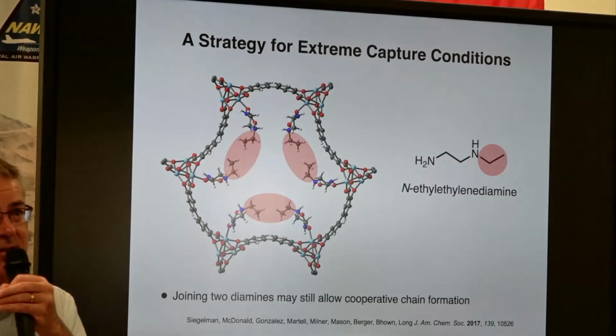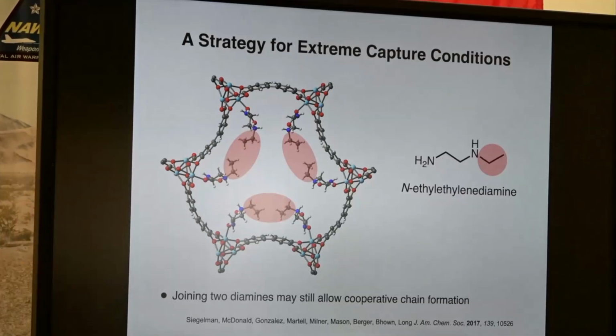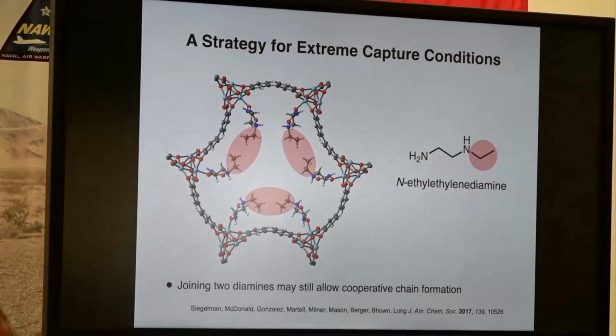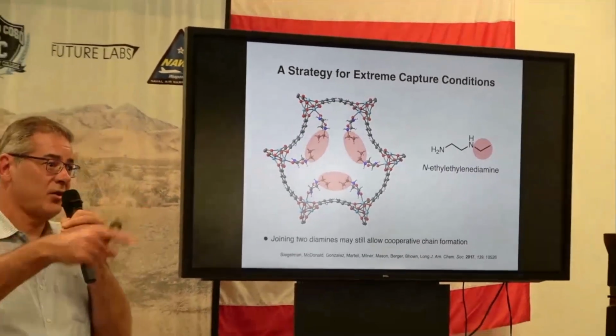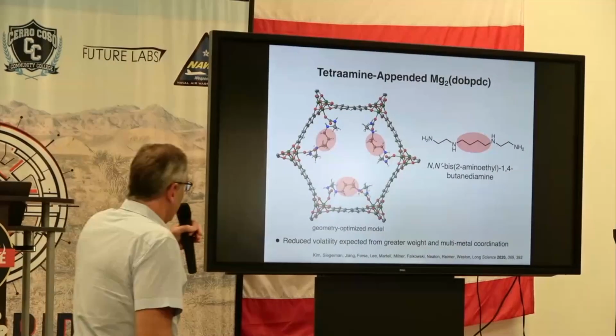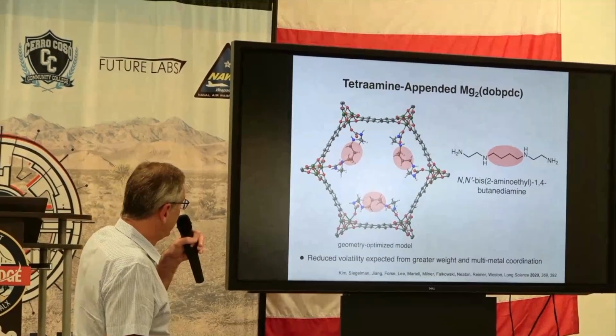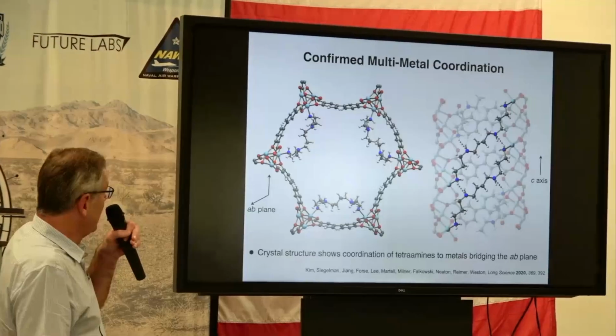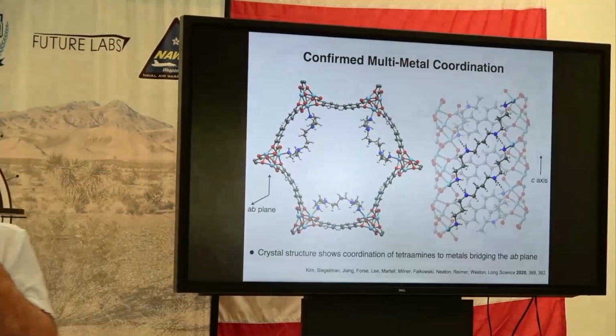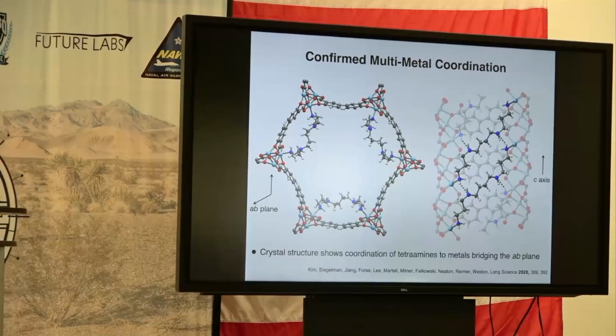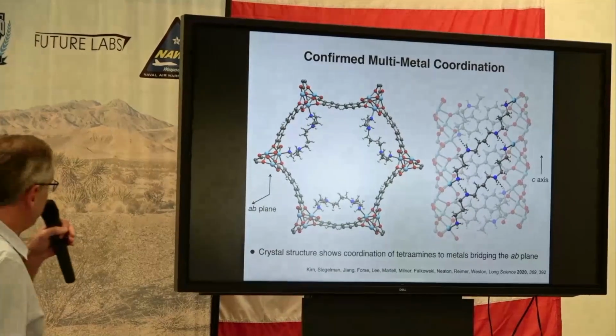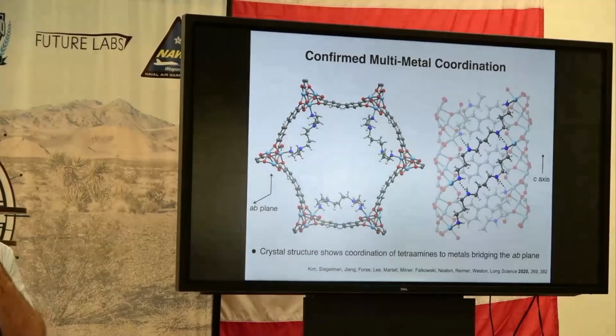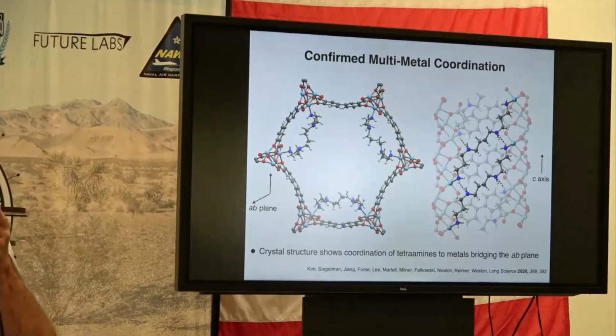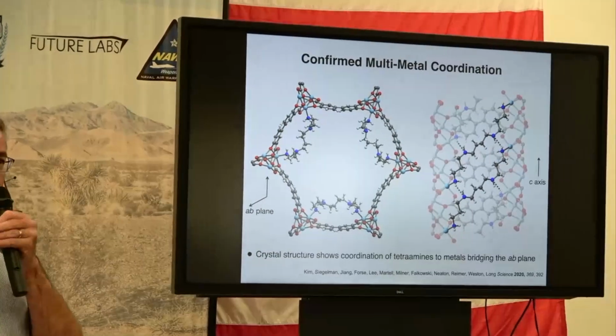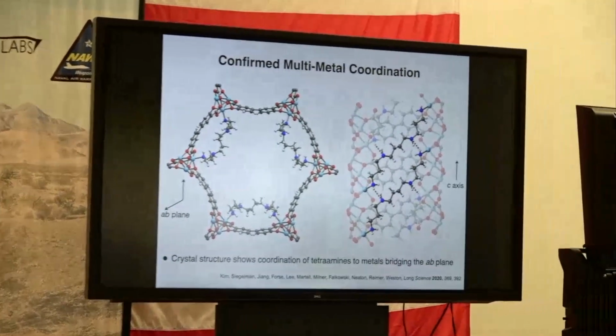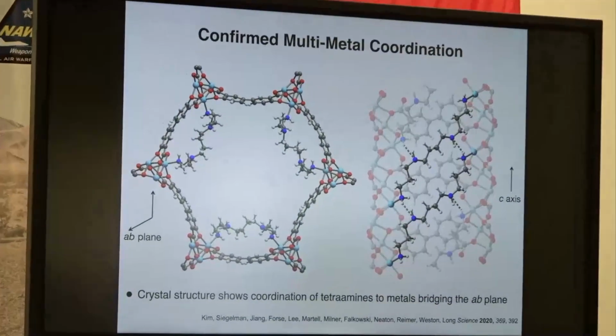We came up with the idea: let's make a tetramine where we covalently tether 2 diamines in a way that should still allow the polymerization reaction with CO2. And so here's one of the examples of a tetramine that we thought should work. And in fact, if you load them in, they organize themselves and you can get a crystal structure. And so there you can see the rows of tetramines. The tetramine has 2 binding sites now instead of just 1. And so they're much less volatile, and we can now go to several hundred degrees C without losing any of the amines in this material.